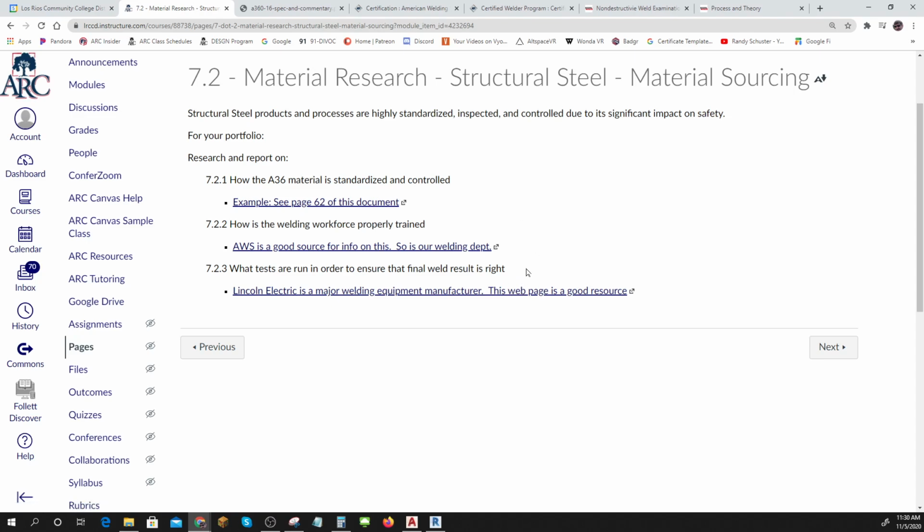But American River College actually talks about non-destructive testing. So one of the pieces of equipment that I got to design was called a weld crown remover. Because when you do a weld, there's usually a bump left over. And that bump makes it hard for ultrasonic testers to do a good test. And if you're doing nuclear power plants, as I said, you need to have a good test. So I actually made a piece of equipment that would track the pipe and slowly cut that crown off perfectly smooth so they could do non-destructive testing in nuclear power facilities. And it's very cool. My name is on a patent. I hold a patent for it. Of course, I don't own the patent. Tritool Inc. does.